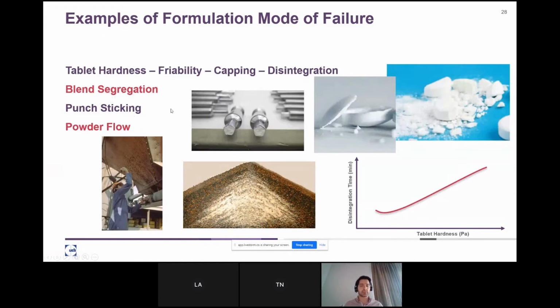Powder blend segregation is also an issue. Here is when we put a powder on and generate a heap. Typically we are talking about multi-component mixtures. We have different components in the formulation, and typically the powder tends to segregate, and it's very critical to formulate the powder such that segregation cannot happen, by mixing some cohesive and free-flowing material. Punch sticking is another issue. During tableting, if the powder is too sticky, it might stick to the surface of the punch, and then you cannot actually form a good tablet.